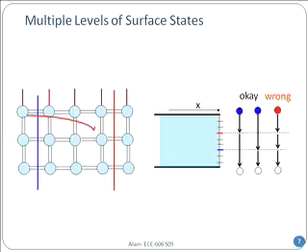The reason is, you remember, although I have drawn this picture in this particular way for my convenience, where all the trap levels look like they are in the same position, they are really not. Look at the picture on the left-hand side, because the blue state came from a region which was the vertical blue cut on the left side. On the other hand, the red surface state came from a region which corresponds to the vertical red line on the right-hand side.